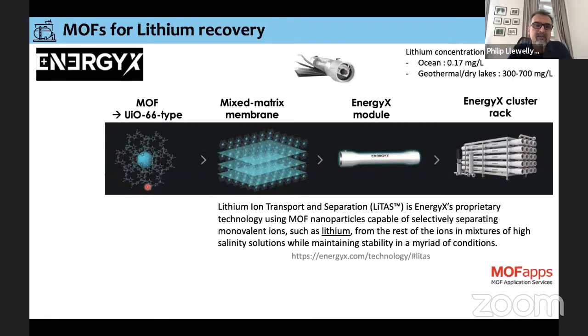Moving away from gases and vapors, this is the use of MOFs for lithium recovery from quite dilute sources. The company's name here is EnergyX, and what they are doing is using a mixed matrix membrane, using a UiO-66 type material. If you look at the publications related to this work, they've taken this UiO-66 and looked at different functionalizations. You can see up here the sort of concentrations we're looking at, whether it's lithium from the ocean or from underground or geothermal areas. The concentrations are actually quite small. So this is what EnergyX claim, and they have a partnership for the UiO-66 material.